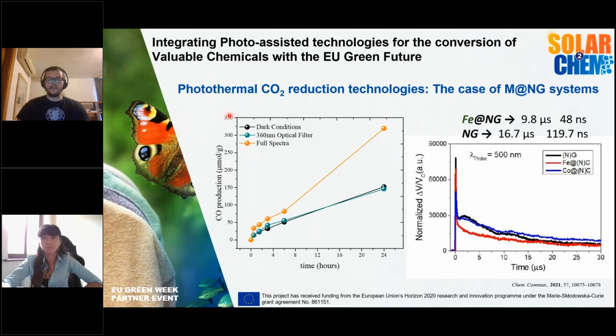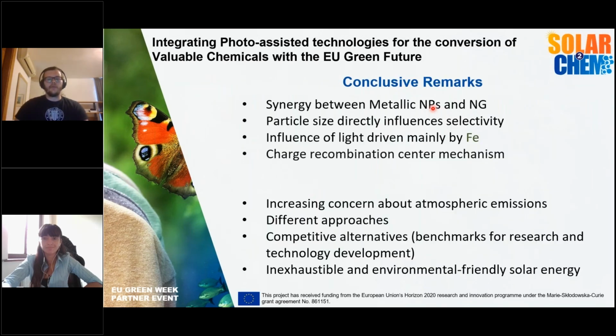The catalyst was inactive in the absence of UV light, which is not good news if we consider later, let's say, using this for solar light, but it was a good clue for us in understanding the mechanism behind it. And the last clue was given to us by transient absorption, where we saw that despite having a higher photoresponse, the iron analog had a much lower lifetime for the charges in both longer lived and shorter lived components. So with everything together, we were confident enough to say that this is indeed a photothermal mechanism, and our catalyst is doing photothermal CO2 reduction.